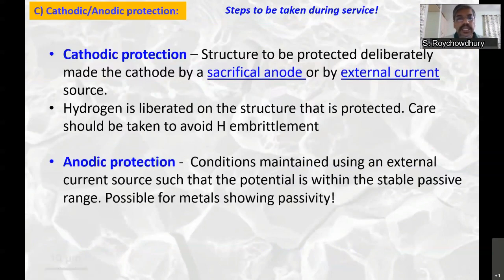Cathodic or anodic protection can be done. Cathodic protection, as I told you, there is no corrosion occurring at the cathode. Corrosion only occurs at the anode. So cathodic protection means you make the structure intentionally the cathode so as to protect it. You can make it the cathode by using a sacrificial anode or by applying an external current source. But one has to take care that hydrogen is liberated from the structure that is protected if it undergoes cathodic protection. Care should be taken to avoid hydrogen embrittlement.